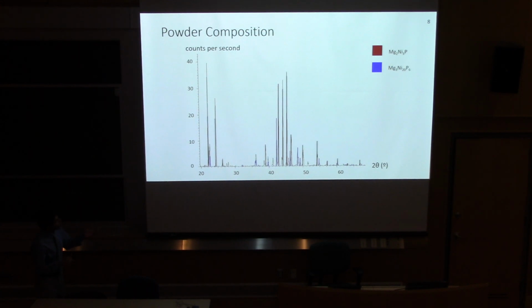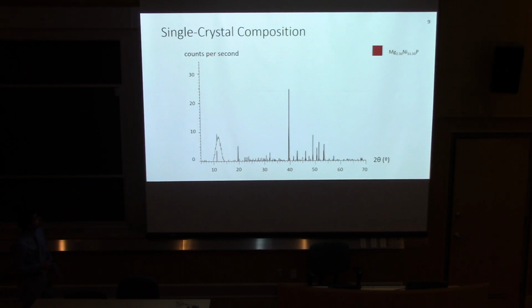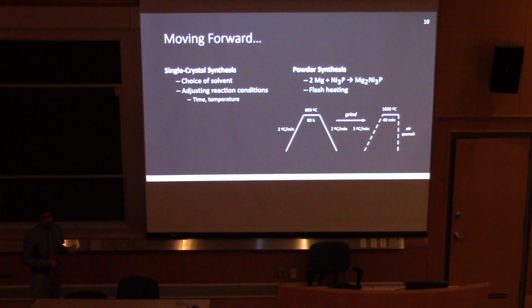So what we see over here is that, yes, we have our target compound, but it's still mixed in with this other polymorph of the nickel-rich phase, which we don't want. And as transition metal phosphides are insoluble in mineral acids, this makes the separation all the more painful, which means that we have to try something else. Additionally, for the single crystal composition, yes, we have a pure phase, but it's magnesium nickel phosphide in a 2.5 to 11.5 to 1 ratio, which is, once again, not our target compound. So what does this mean?